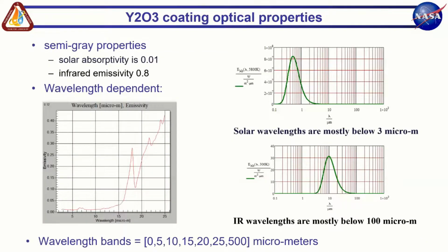So now let's look at this optical coating, yttrium oxide. We took a semi-gray, constant properties approach. We have two models, one with constant properties, one with wavelength dependent. We'll look at the constant properties first. Solar absorptivity 0.01, so it's pretty low, and emissivity 0.8. We don't actually have that data, but it's probably a pretty good estimate.